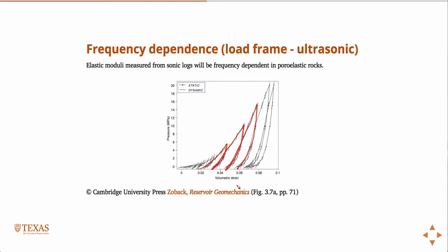The solid lines I traced are a result of direct measurement of the pressure-volume response. Likely the pressure was controlled by a fluid bath — the sample was placed in a fluid with a membrane around it, and the pressure of that fluid was increased. If you're asking whether those lines would ideally have the same slopes — without rate effects, yes. The fact that they don't have the same slope is due to the viscoelastic property. Let me finish explaining the difference between what's labeled as static and dynamic.